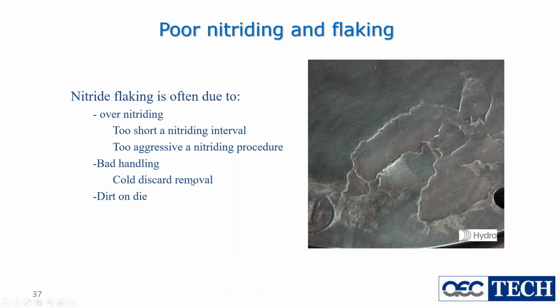So there's two things that can go wrong. If you take the nitriding so it's too thick and you have a poor layer between the diffusion layer and the actual bulk of the steel, you can get this flaking. This is a picture of a die actually from South Wales in the UK. And this was a double problem. One, we were too aggressively nitriding the die, but secondly, when the die was removed from the die ring with the bolster leaving a piece of aluminum on the die, they were cold shearing it off the die face, and that put additional stresses into the layer and caused this peeling of the steel. There's also some suspicion that when it went in for some of the nitriding processes, the die may not have been as clean as it should have been.